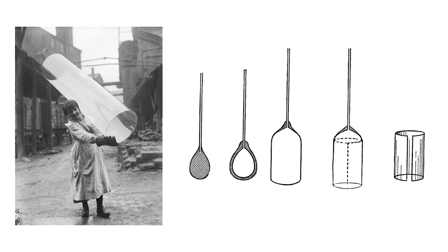These long cylinders would have the ends cut off square to the cylinder, and then the cylinder was scored lengthwise and placed back into an open door furnace. The score mark was cracked and the glass would open up, and if everything went well, that cylinder would lay down and form a piece of glass. This was the beginning of larger and larger panes of glass, a far cry from the 6 by 8 inch crown glass of the 1700s.